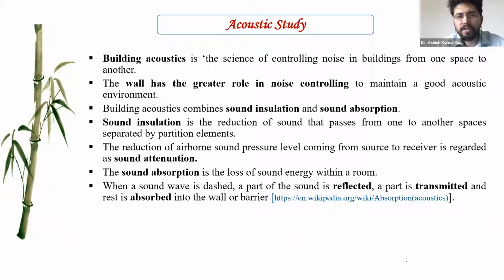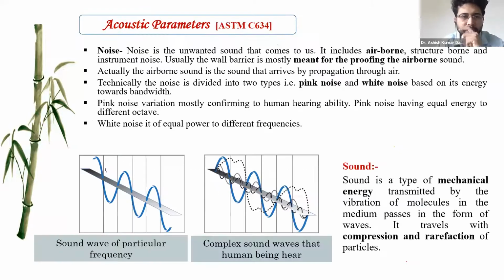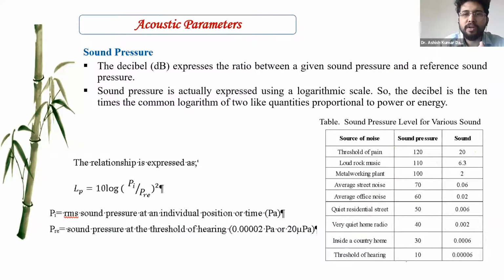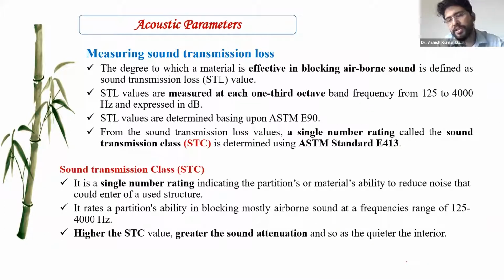So this acoustic insulation study was conducted to find out the sound transmission class. We found that the higher the sound transmission class of the material, the better the insulation effect. So as per the ASTM standard E413, we conducted the test for finding the single rating number, that is the STC.